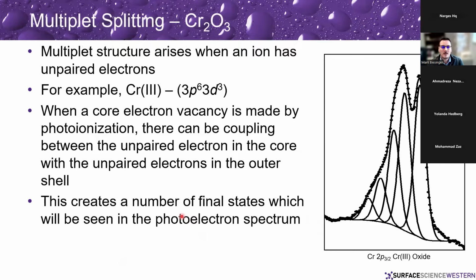If we look at something like multiplet splitting, multiplet structures arise when an ion has unpaired electrons. So, for example, chromium-3 is 3p6, 3d3. And so when you have a core electron vacancy being made by photoionization, you can then get coupling between the unpaired electron in the core with the unpaired electrons in the outer shell. And this will create a number of final states which will be seen in the photoelectron spectrum. So instead of a nice single peak here, you get all this structure showing up within the spectrum.